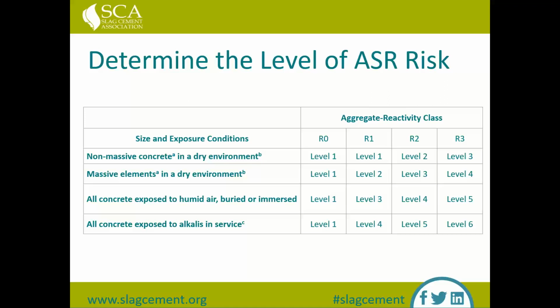The next step is to determine the level of ASR risk. From the aggregate reactivity class we just obtained, we compare that to the size and exposure conditions. Aside from R0, which is level 1 for each size and exposure condition, the level of ASR risk increases as we go down the list, and increases from the top left corner to the bottom right, from a level 1 to a level 6.